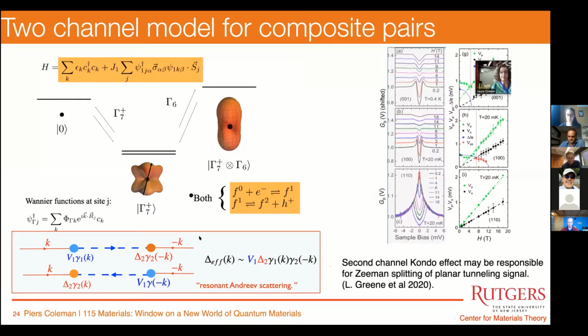So Rebecca will tell you more about that this evening, but one of the things that I find very interesting is the possibility, as yet unproven, that this kind of mechanism might be important for these fascinating new planar tunneling measurements of the group of Laura Greene. And what they've seen is that even though we know that the coherence temperature of the system is about 40 or 50 Kelvin, and that we have Kondo effect turning on in a coherent way at higher temperatures, we seem to have a low energy scale, which is Zeeman split by the time you get to about 5 or 6 Tesla. And so this suggests that there may be two components to the Kondo effect, and this second channel Kondo effect may be responsible for the Zeeman splitting of this planar tunneling signal and might be a contender for the pairing in this system.